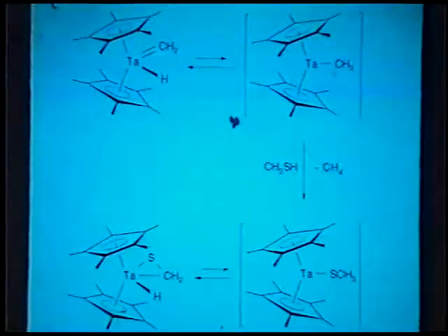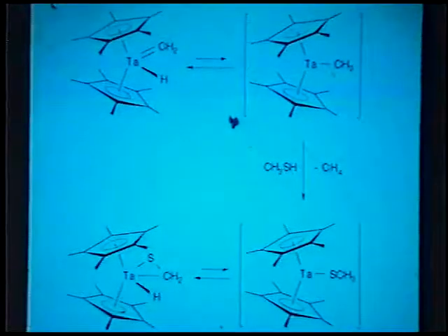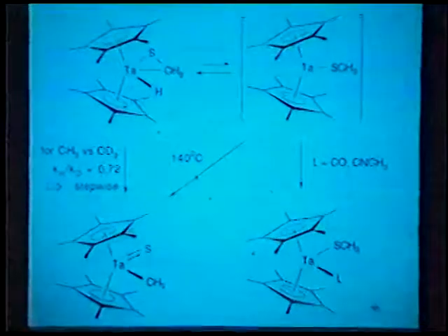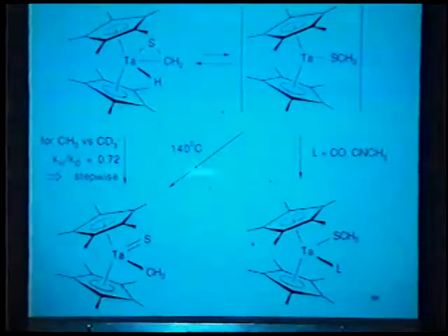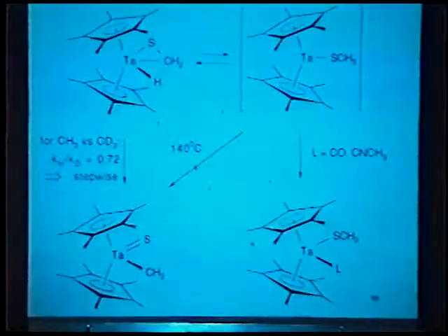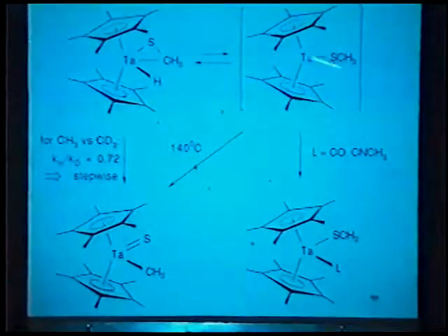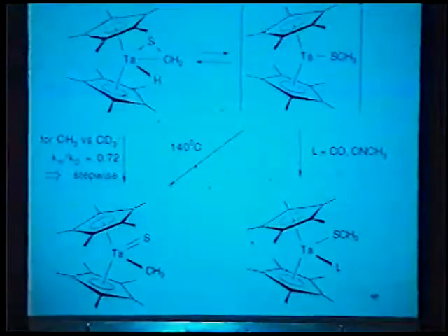On the other hand, with sulfur, we might like to break that bond, and indeed, exactly analogous chemistry happens with methane thiol as it happens with methanol. Here's a great example of how ChemDraw can come to the rescue. You simply go in and change a few atoms and copy the same file again, changing a few of the numbers like the inverse isotope effect. But again, analogous chemistry, and here we are doing a very clean carbon-sulfur bond cleavage reaction. We're now asking questions about the stereochemistry of the migrating carbons, the kinds of questions that physical organic chemists often ask about